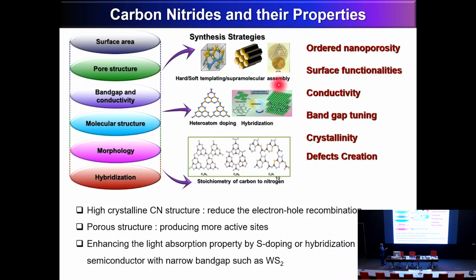To increase the specific surface area, we have introduced ordered mesoporosity in the carbon nitride material. Thereby, you have a material with a very high surface area and large pore volume, and that can increase the number of active sites in this organic semiconductor. The second strategy is to introduce surface functionalities by replacing some of the nitrogen atoms with carbon, sulfur, phosphorus or boron, so that you can tune the electronic properties of this material.